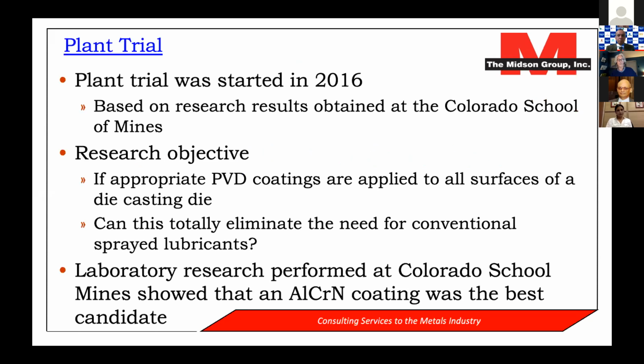The research objective, as I've talked about before, is: if we pick an appropriate PVD coating and apply it to all surfaces of a die casting die, can we totally eliminate the need for conventionally sprayed lubricants? Early on in the project, there was a lot of laboratory research performed at the university, at the Colorado School of Mines, and that showed that an aluminum chromium nitride coating was the best candidate. And so that was picked for the plant trial.